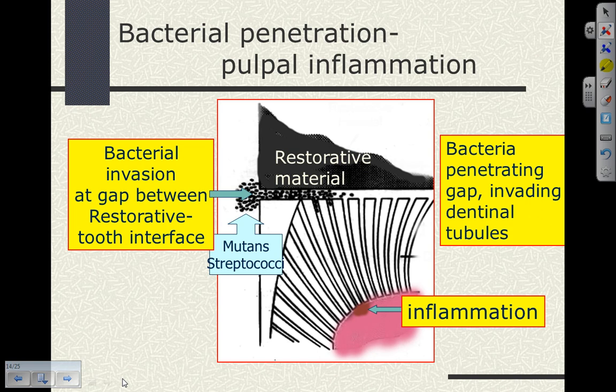So when we talk about bacterial penetration and pulpal inflammation, we're looking at a gap, bacterial invasion between the restorative material and the cavo surface margin. The bacteria are entering the tooth interface at a microscopic level, entering the dentinal tubules, and in this case we're looking at Streptococcus mutans, mutans streptococci. The bacteria are penetrating the gap. They're going down the dentinal tubules. They're causing inflammation of the odontoblastic processes until finally you see a localized inflammatory response at that leading edge of bacterial toxins.